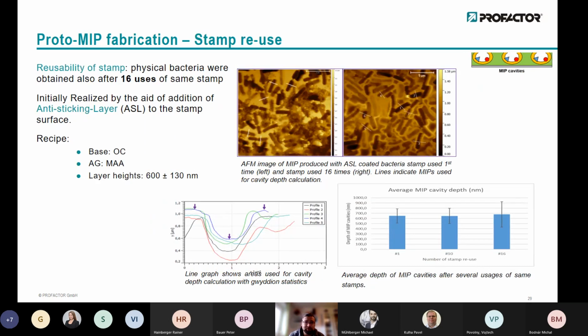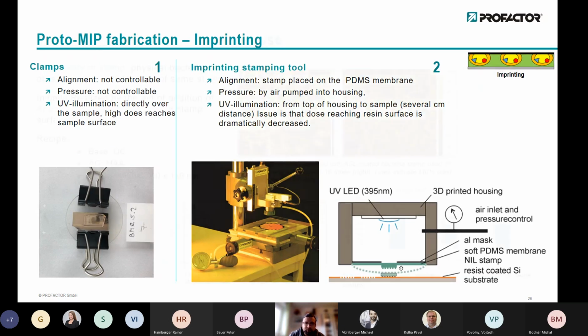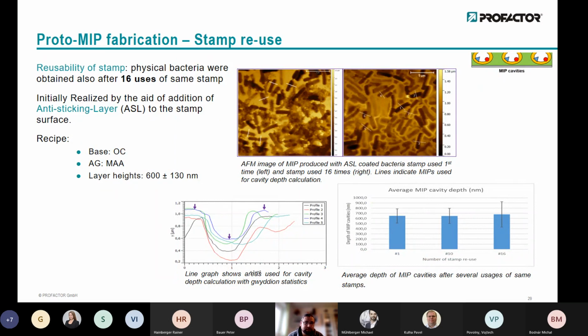Sorry for the background noise if this was heard. We reused the stamp several times since this was a goal. Or basically, let me get to the result here. We reused the stamp at least 16 times: stamping, reintroducing the anchor group, stamping again, and so on, at least 16 times. And here are the two AFM pictures showing that the cavities that are formed are indeed there and are comparable. So also from thickness and so on, from the profiles, you see that they are quite comparable. The average MIP depth is still the same.